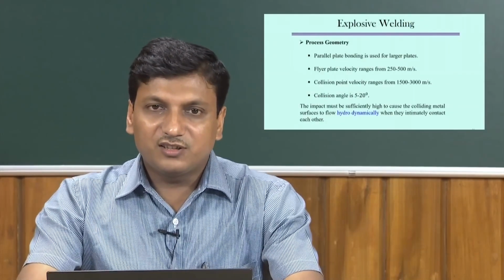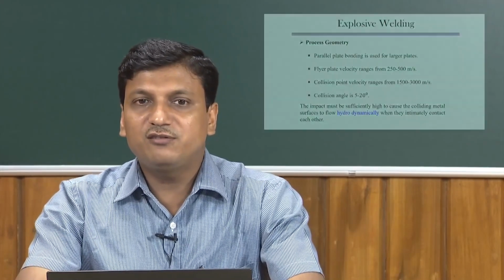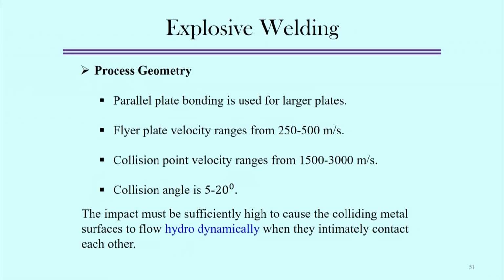We can see the process geometry of explosive welding. Parallel plate bonding is used for large plates, so two parallel plates can be used, and the flyer plate velocity ranges from 250 to 500 meters per second. At the collision point with the application of the explosives, the collision point velocity ranges from 1500 to 3000 meters per second, which is a very huge velocity. And the angle is also an important parameter, around 5 to 20 degrees.